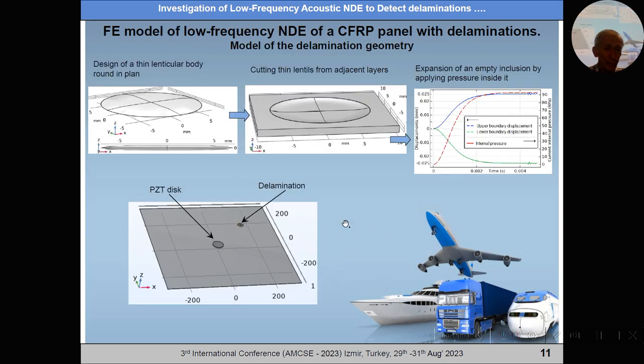The geometry of the model fully corresponded to the real panel with the delamination and installed piezoelectric transducers. To exclude significant thinning of the layers in the presence of delamination, a very thin lenticular body was first created and included between adjacent layers, then removed inside it. In order to obtain the desired real thickness of the delamination, the pressure inside it was increased to expand this thickness.